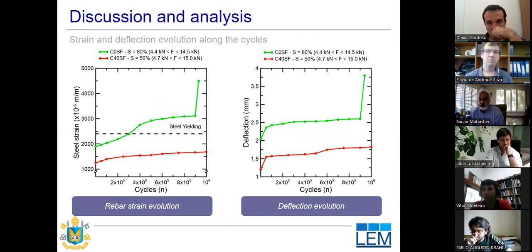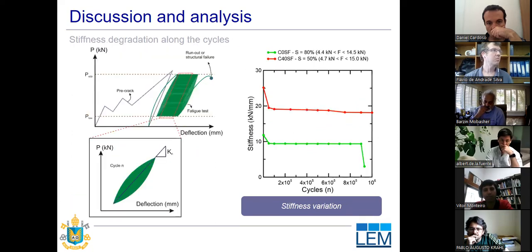And the same phenomenon can be analyzed for deflection, since the use of fibers can enhance the stiffness of the reinforced concrete structure and diminish the deflections of the overall structure along the fatigue life. Now we have the stiffness decay. Once again, with the use of fibers, we have higher values of stiffness along the fatigue test.